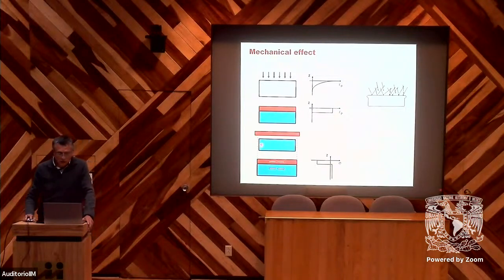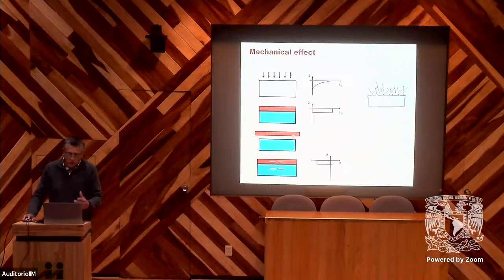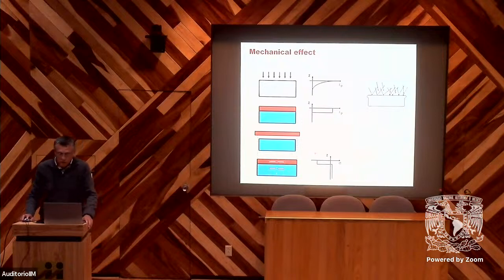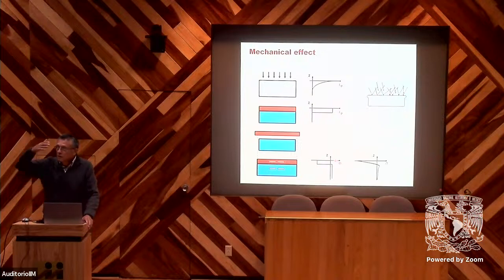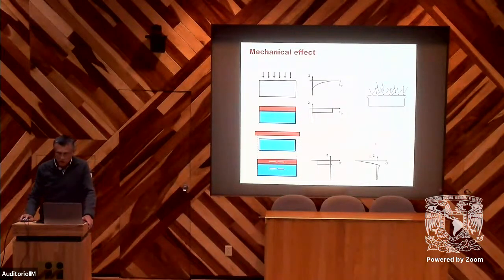If we have separated parts, we don't have any force, any residual stresses. But we have the continuity of the material. That means this deformation will be prevented by the bulk of the material. So we will have compression near the surface, and this will be balanced by tensile stress inside the material. And of course, this is a simple example. If we consider that we have a gradient with continuous variation, we will have such a distribution of residual stresses. That means we have compression equilibrated by tensile inside the material.